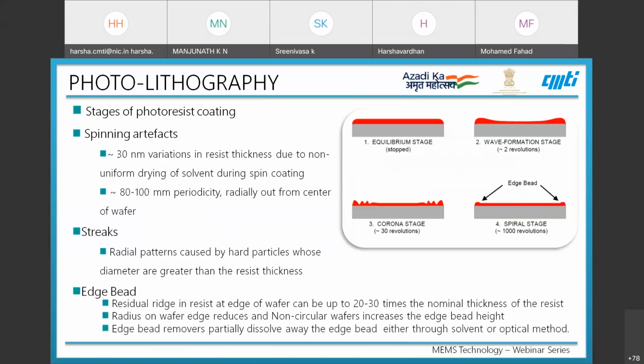So when we do the spin coating, the different stages of photoresist coating can be divided into four. The first one is the equilibrium stage. Once the photoresist is completely coated, there is a wave formation stage at approximately 2 revolutions.